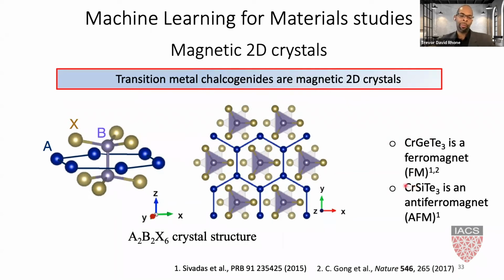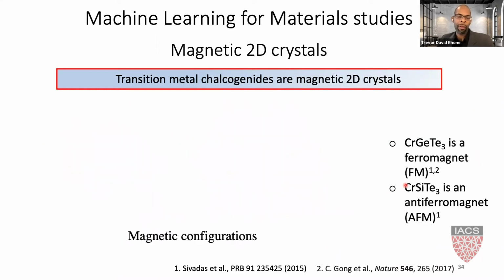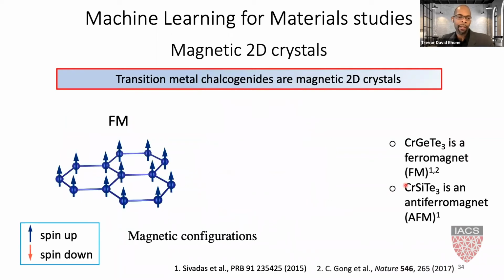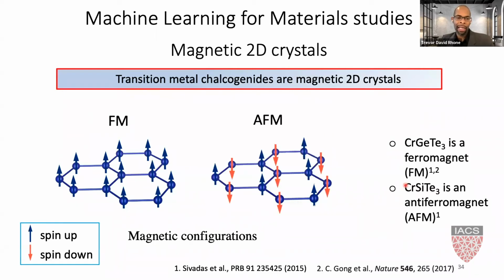This is really surprising for me because germanium and silicon are in the same column, and they're not magnetic atoms. But by changing germanium to silicon, you can change the magnetic order. So there's clearly a structure-property relationship here. Chromium germanium telluride is a ferromagnet, where all the spins are aligned, and chromium silicon telluride happens to be anti-ferromagnetic, where the spins are anti-aligned. So there's definitely a structure-property relationship happening here.